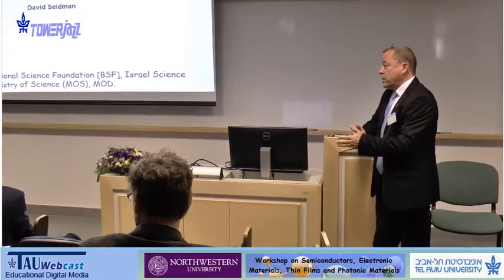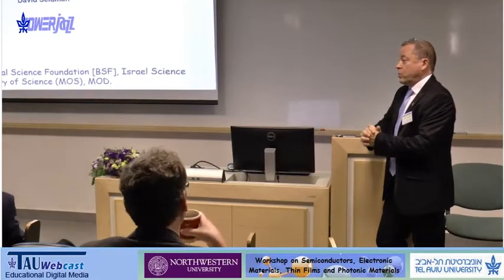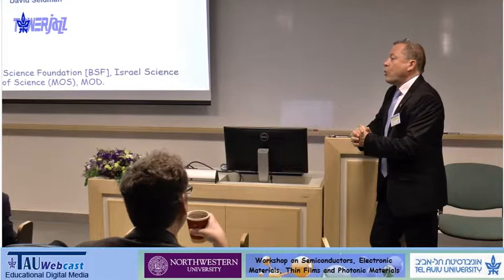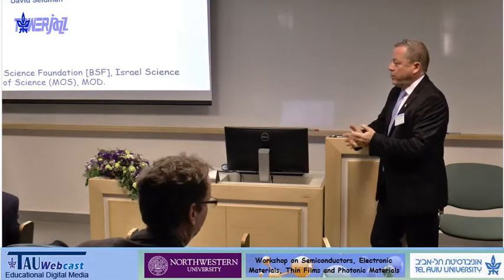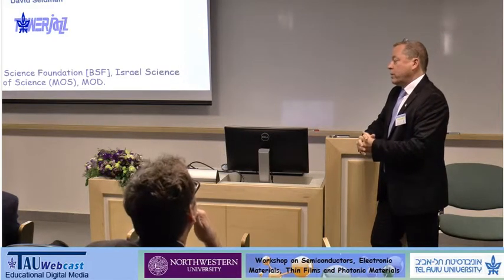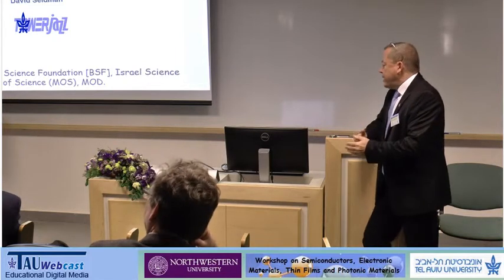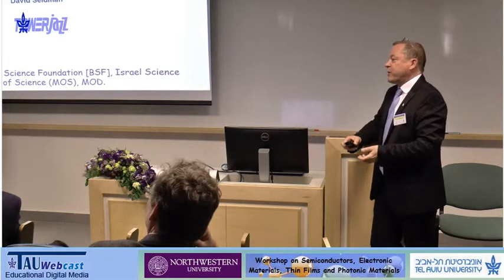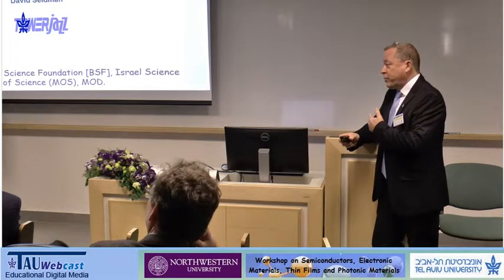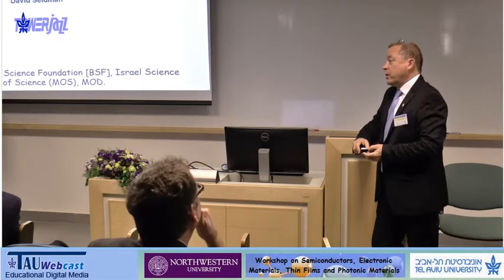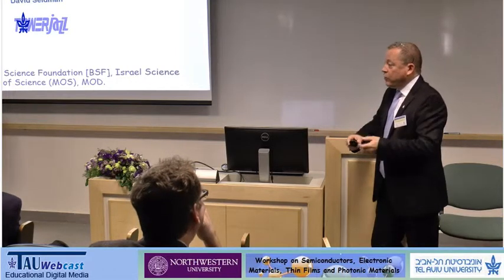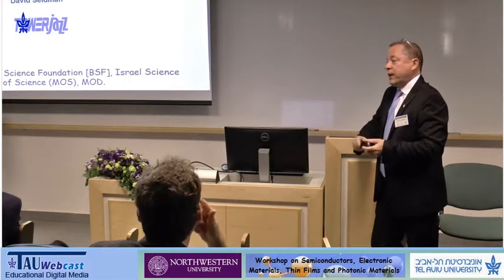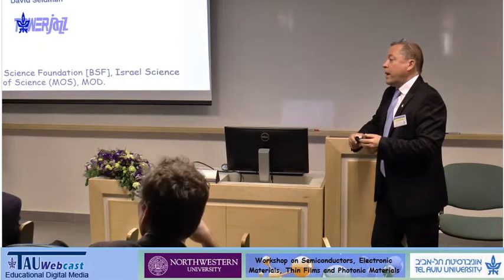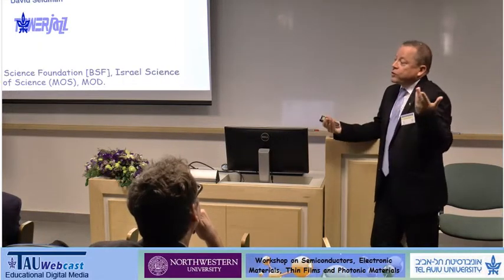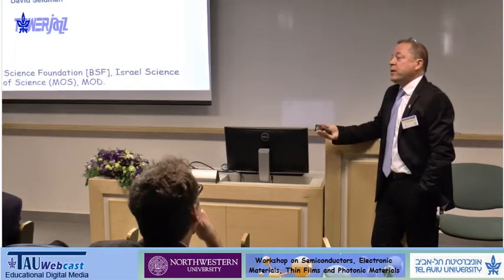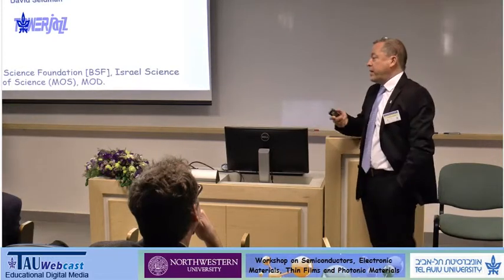The KPFM measurements are all at room temperature. Of the detector? I haven't shown it, but we have time traces, certainly. If you want to know the time constant, it depends on the concentration. As the concentration is higher, the response is faster. It's seconds for high concentration of ethanol, tens of seconds for very low concentration. The recovery is only after annealing, after we heat it to 50 degrees. Probably similar time constants. After the ethanol is absorbed, you need to desorb the ethanol. But at 50 degrees, this can be done in situ within the transistor. This is the idea, and we are working on this now.